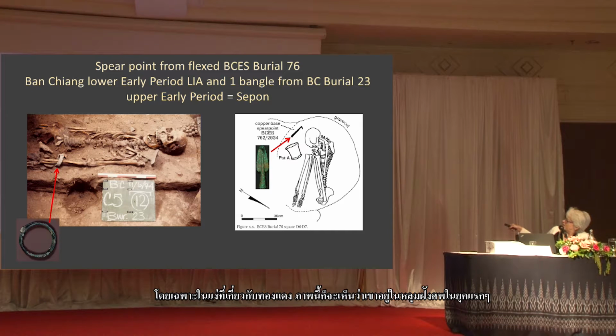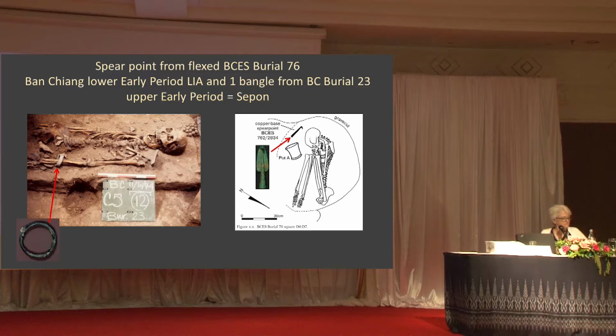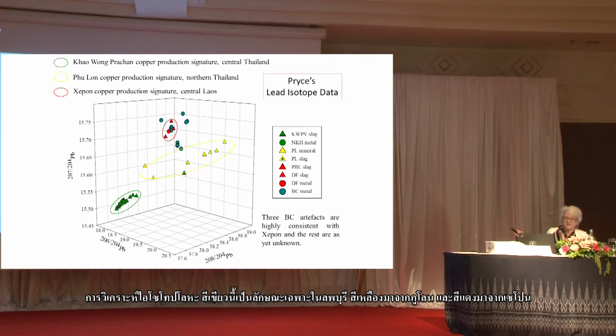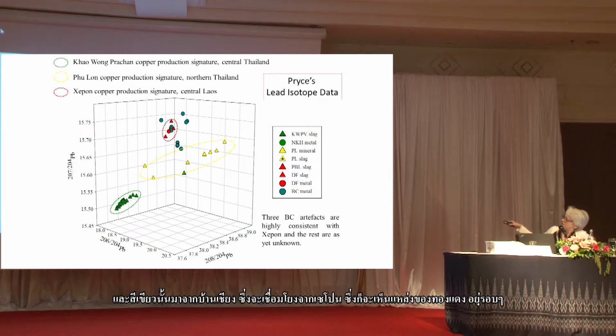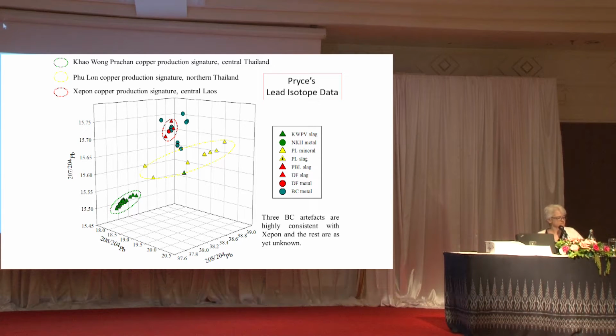This is just a picture of where the spear point was found in a flexed grave in the lower early period. So this is what a lead isotope analysis looks like. The green here is the Khao Wong Prachan Valley signature in Lopburi. The yellow, very broad, is the Phu Lon signature, and the red here is the Sepon signature, and those 3 green circles are the 3 artifacts from Ban Chiang that can be linked to Sepon, and then you can see the other green circles are outside of any known copper source.